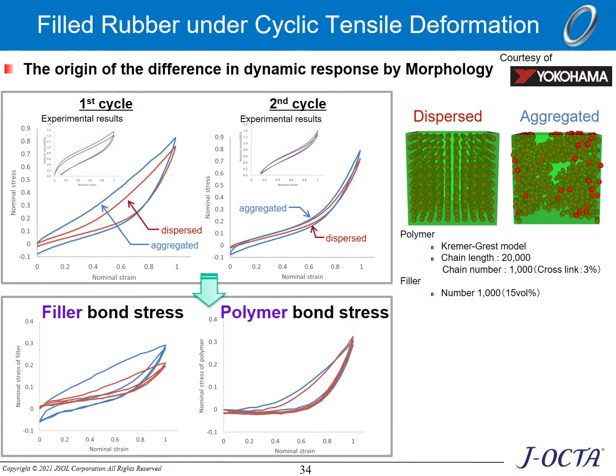The graph on the left shows the first cycle. You can see that the curves do not match up during the tensile and compression processes. This is called hysteresis loss. You can also see the difference between the blue line, which shows the aggregation structure, and the red line, which shows the dispersion structure. You can see a small graph at the top left, which is the result of the experiment. You can see that the simulation results are close to the experimental results.